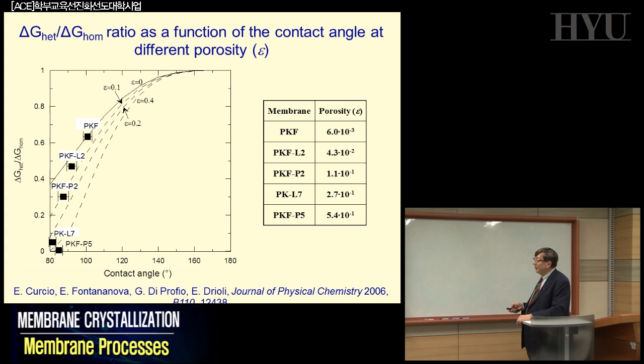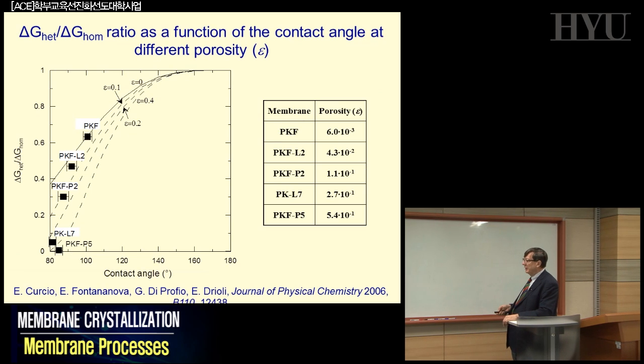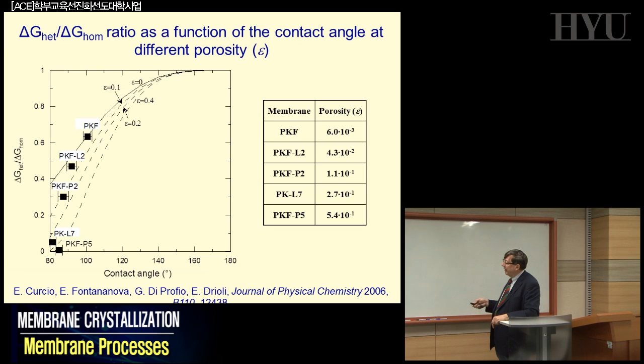To the point that, again, this delta G heterogeneous compared to the homogeneous one, if you study carefully as a function of the contact angle, you will see that it is not only a function of the surface energy of the different polymer you're using, but also of the level of surface porosity. So this epsilon that we introduced already, which is the effective porosity of your material, but basically the surface porosity. Part of the surface there are pores, part is not. So this is quite interesting and is present here. And if you go from surface porosity 0, you have this kind of phenomena, otherwise you have the other ones, 0.4, 0.2, 0.3, etc.